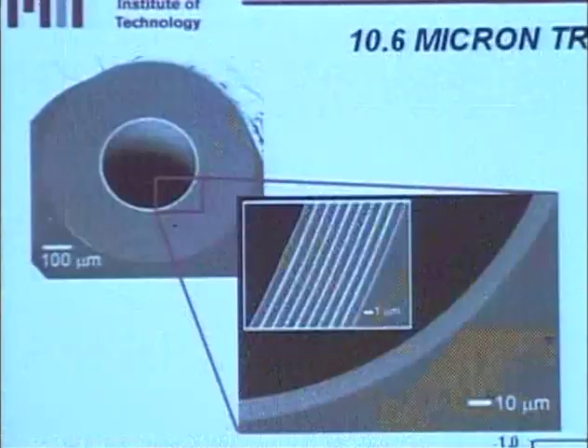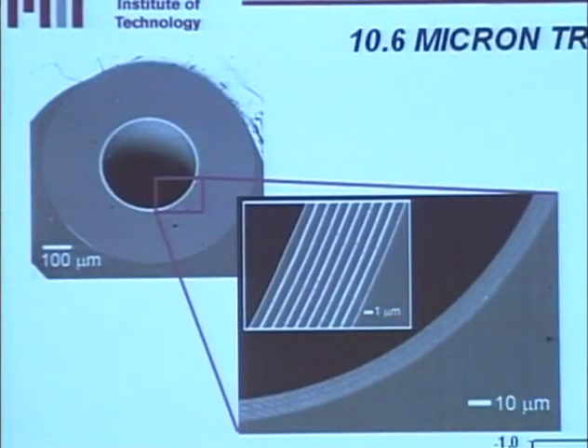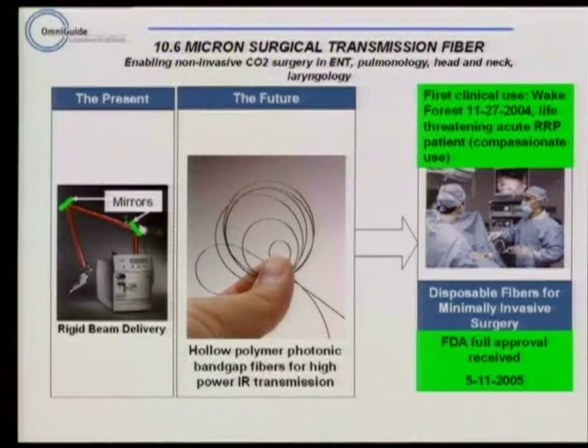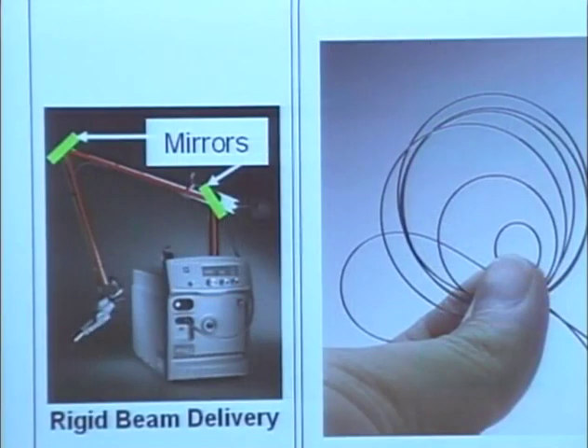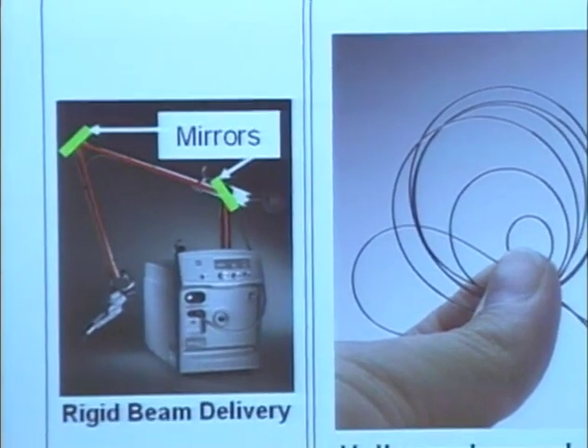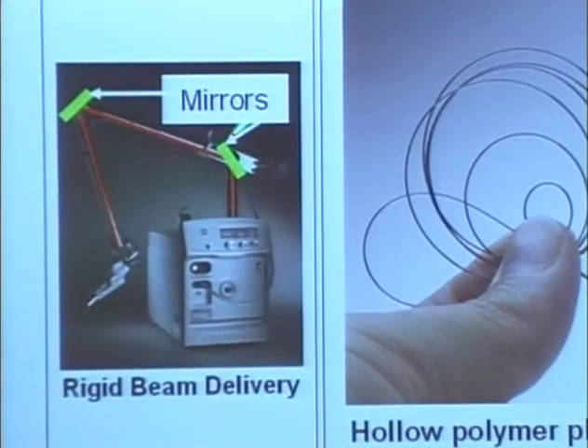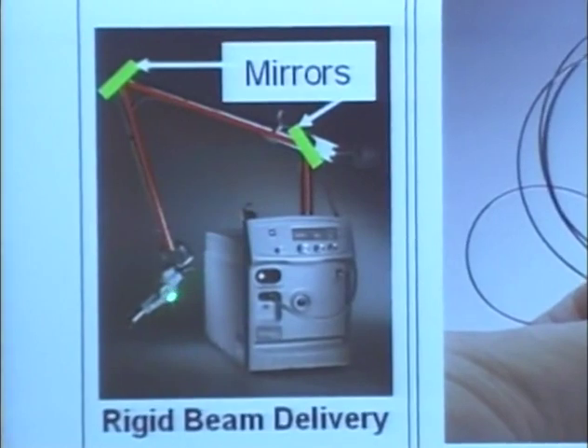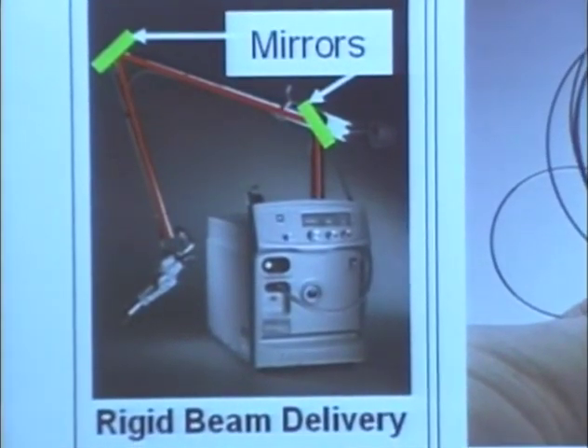Because light, in fact, is contained not in the material, but in the hollow core, and the materials themselves could be almost opaque. So the first application is actually that of non-invasive surgery at 10.6 microns. The idea is to take laser light coming from a CO2 laser, which is readily available in medical centers, and use it to treat and remove growths from the patient's lungs or airways, instead of using a handpiece and a line of sight technique.